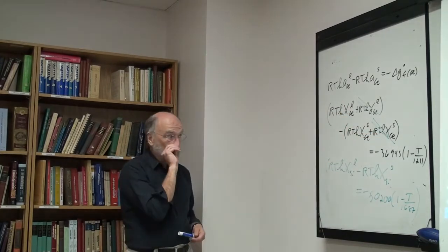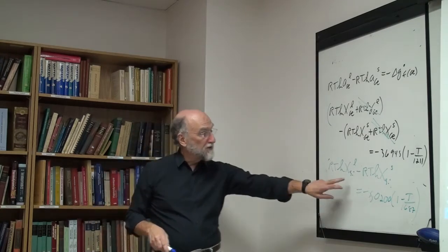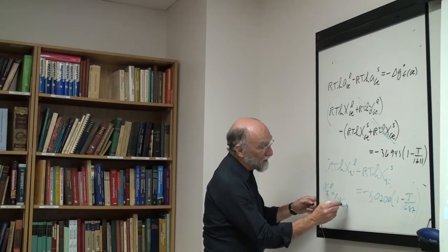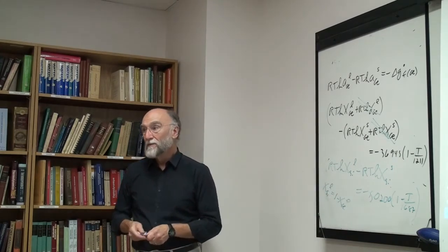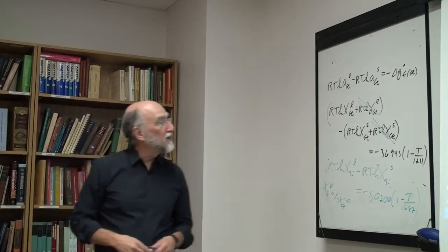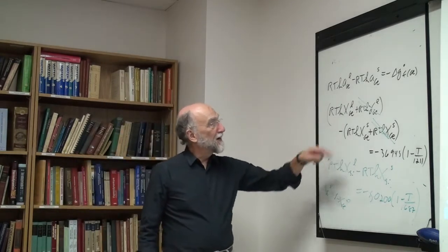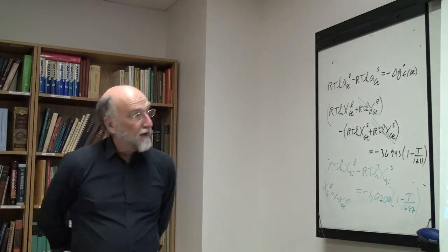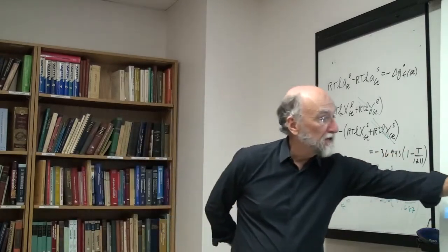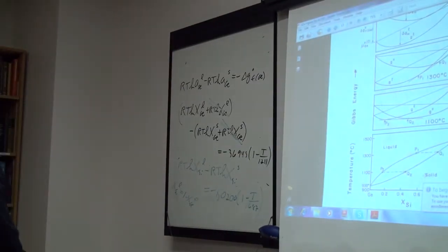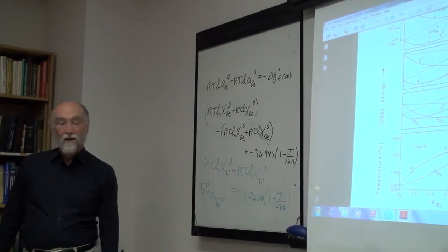Now these are actually quite simple to solve. Remember, X silicon on the liquidus is 1 minus X germanium on the liquidus, and the same thing for the solidus. If you think about it a bit, you're actually solving for log X in the two cases, so you can work it out as two linear equations, really. You pick T to be 1373 Kelvin. Put that into these two equations and you get two equations and two unknowns, X solidus and X liquidus, and solve the two equations. I won't do that for you, but it's very easy to do.